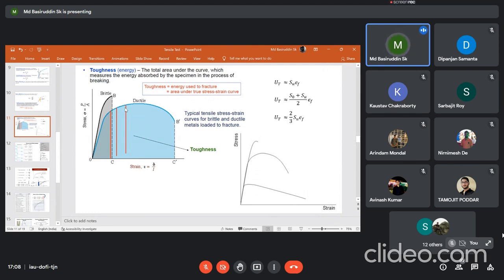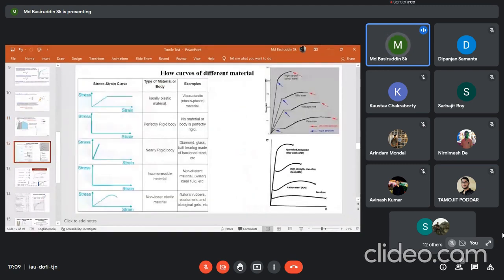Why that happens, I will talk about a little bit later on. But the thing is, whatever mechanical working you do on the material, that leads to an increment of the strength of that particular material. So that is why you will find that by just doing heat treatment, you have developed a material, and then you do a tensile test. Then whatever curve you find, if you do some amount of mechanical working like rolling,